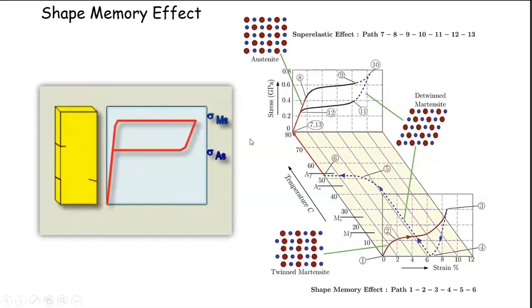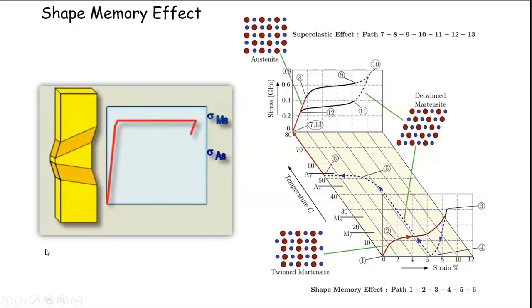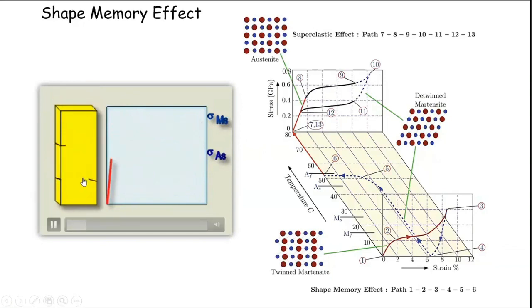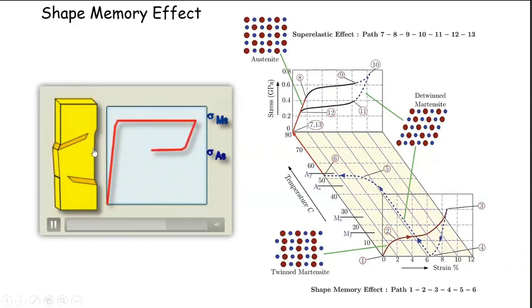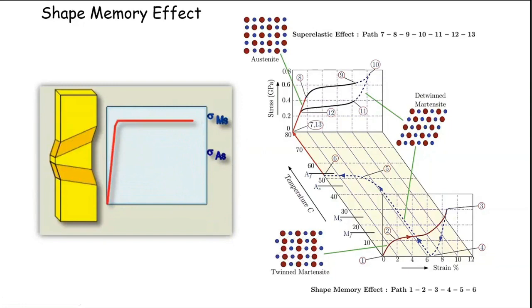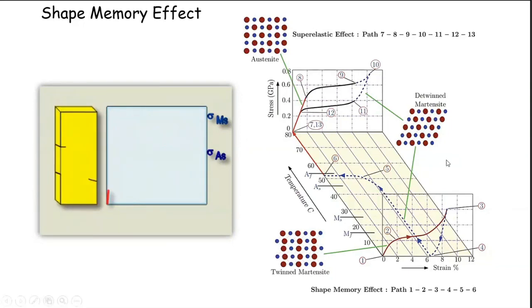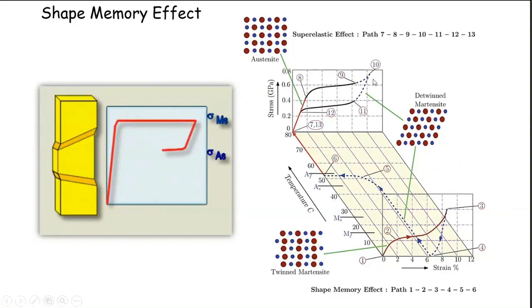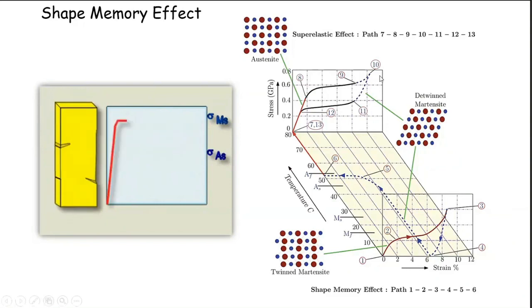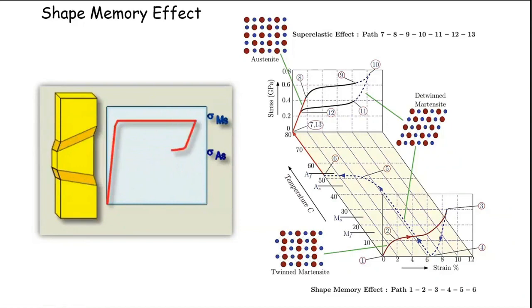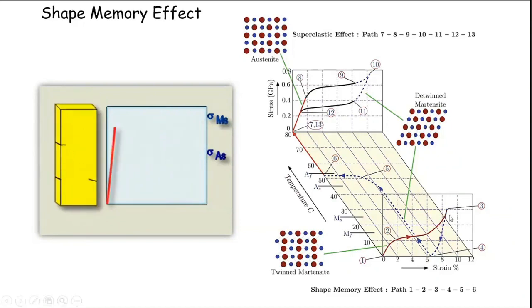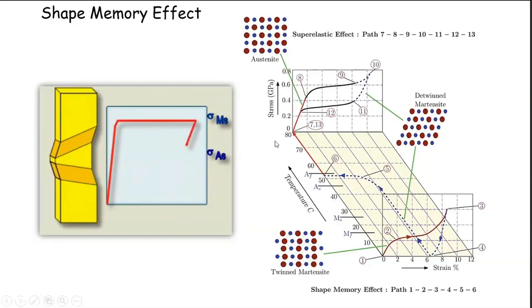Here, this animation shows you that there is a single crystal of austenite, and when you deform it, you have the martensite crystal nucleating and growing, and the plateau corresponds to the constant stress at which the martensite will more or less grow to its maximum, and that will be when the whole sample is consumed. And this will show a maximum strain of about 6% or 10%. That is about, in these alloys and nickel titanium, what you expect to see. And that is the same as what you will get if you had started with that soft and pliable condition. And when you unload it, it will go back to its original shape again, because this martensite is not stable at this load, and you have stress induced after all, and it will return back.